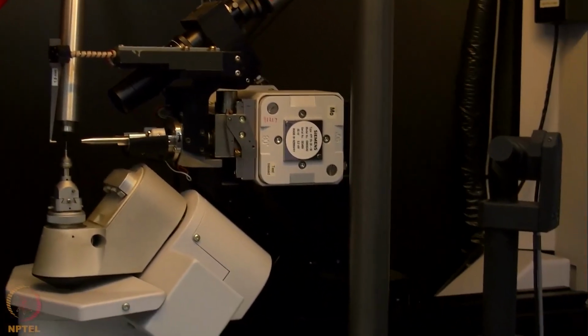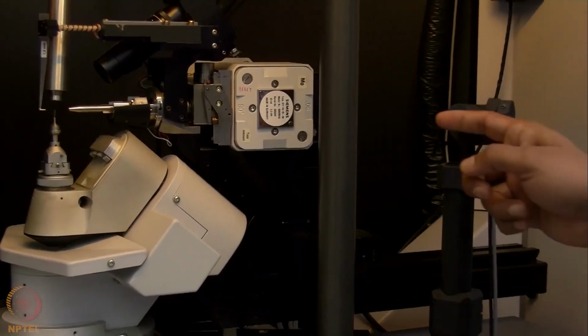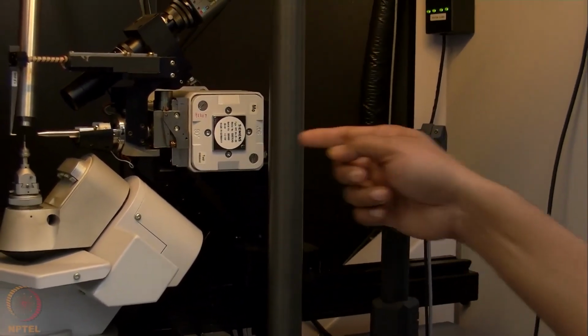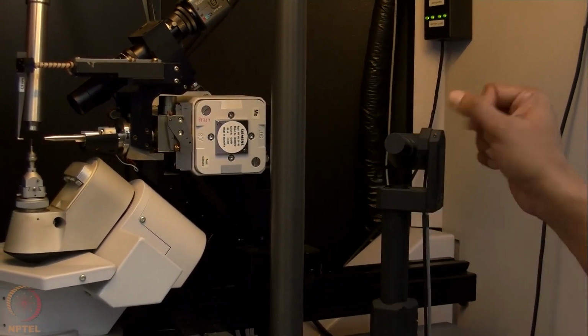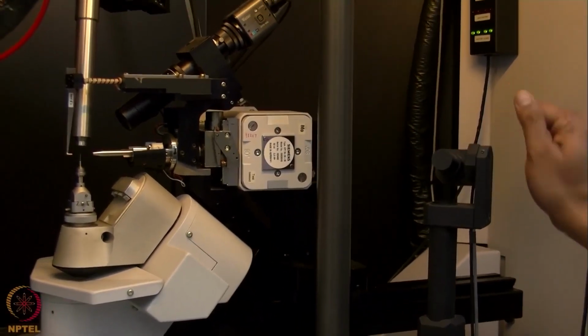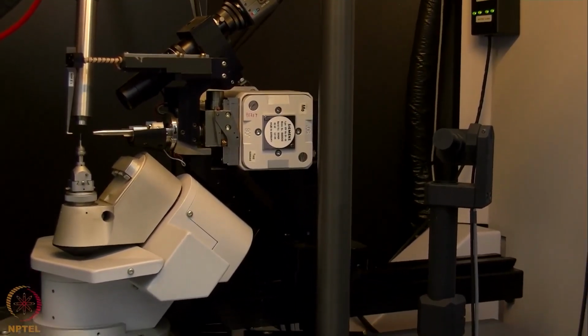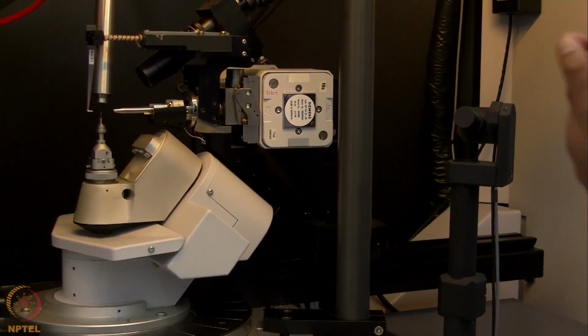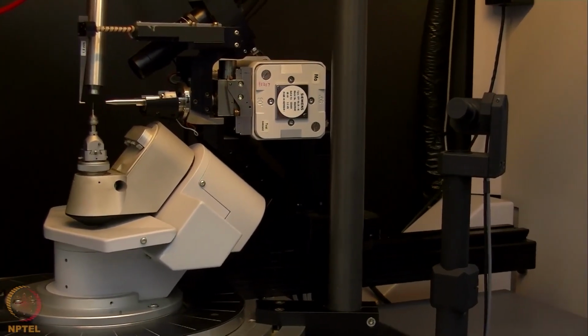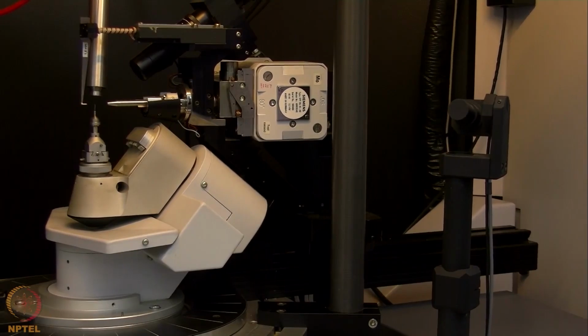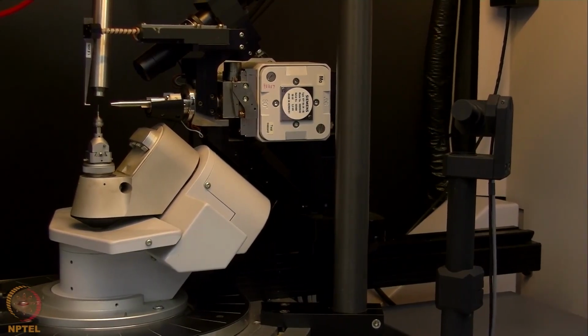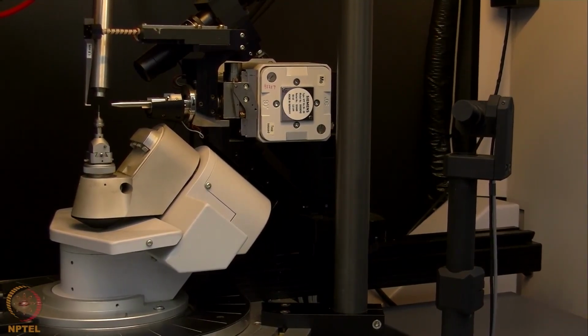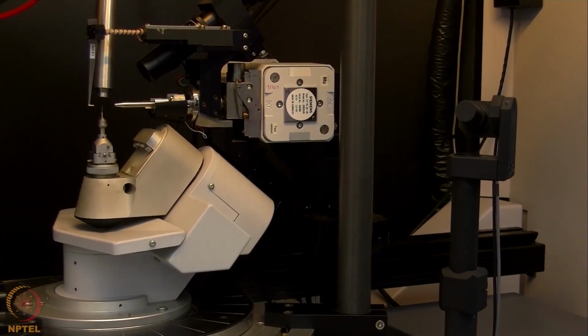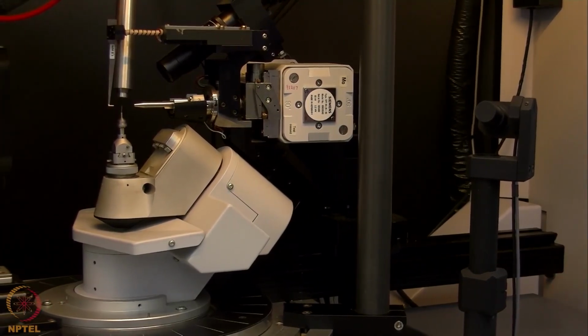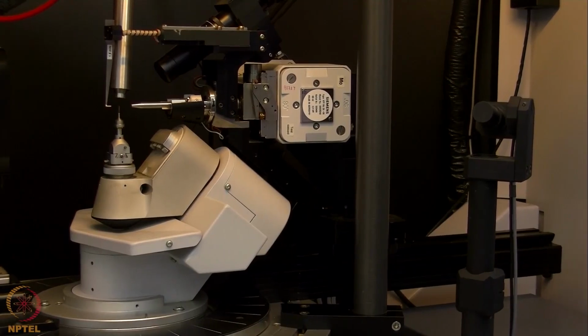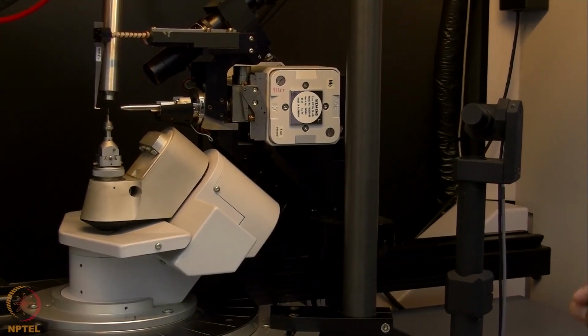So what we do is we try to align this beam, that is the CO2 laser, from here by rotating this mirror carefully using hand and tightening or loosening the screws, and then align it on the capillary, and then slowly increase the laser power to such a value that it can melt the material inside, and then we can do in situ crystallization using the laser.